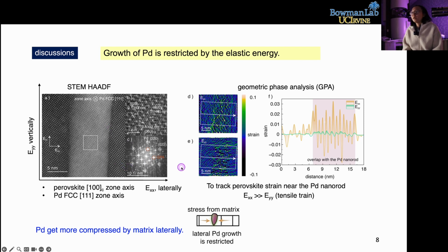Then we use geometric phase analysis to track lattice distortion of the perovskite matrix at the region overlapped with the palladium nanorod. So this is the GPA analysis. The EXX is identified by this horizontal direction or lateral direction. The EYY represents the vertical direction, that means the thin film growth direction.